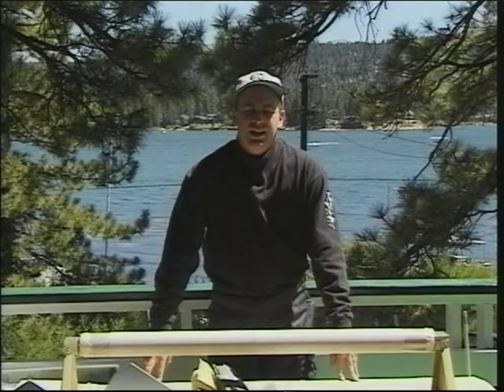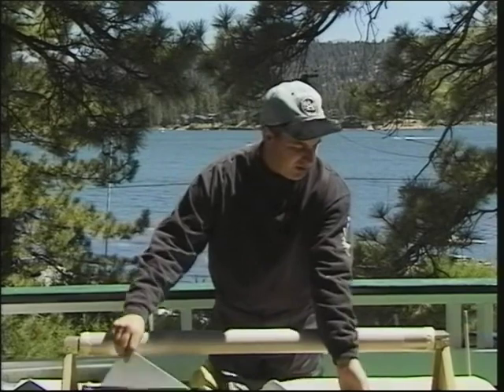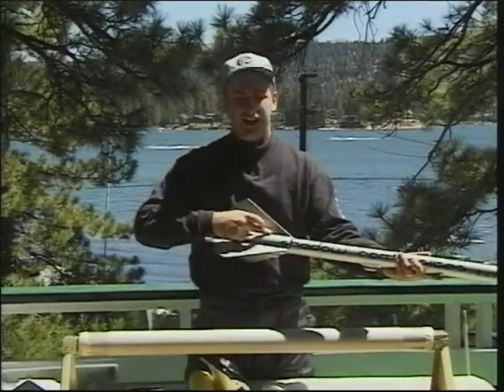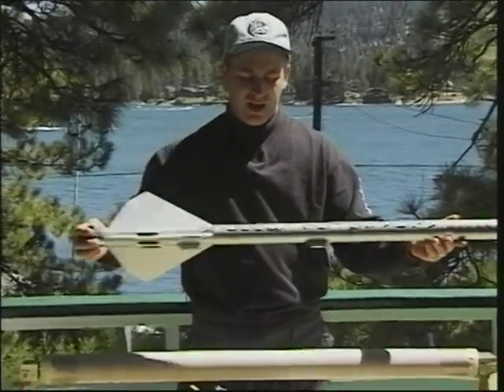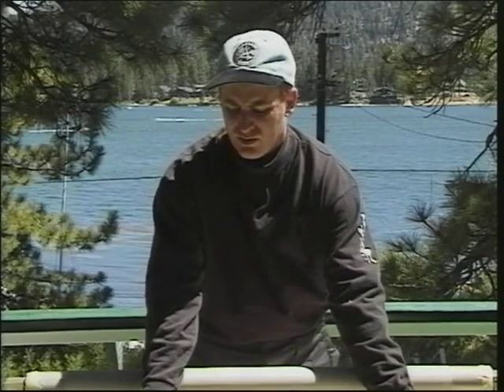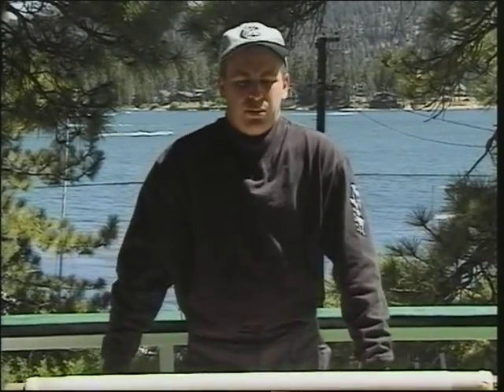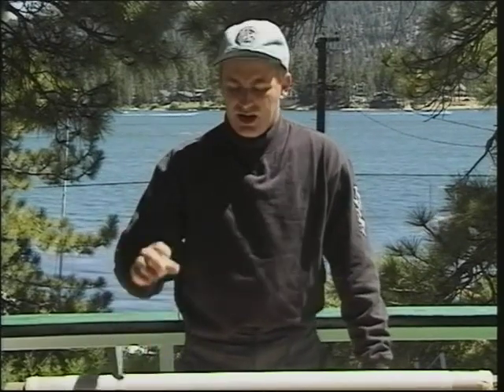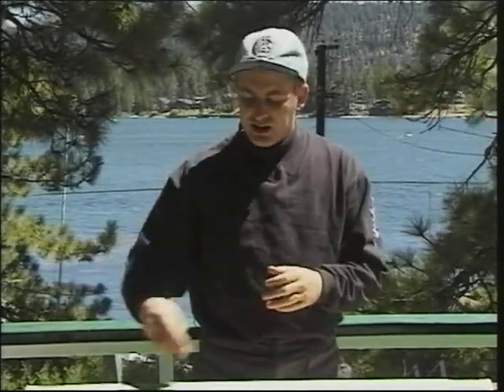So when you're creating things like fillets, and here I've got a couple of the Shadow Composites Raven rockets, the little fillet areas that attach the fins to the airframe, there's a couple different ways of going about that. If you're creating an epoxy structure on your airframe tube, you want to use a fillet material that's made out of epoxy as well. When you rough up the structure of the glass surface after you've completed that, that'll provide a good mechanical tooth to it, so the fillet material will grab onto it. But you also want somewhat of a chemical bond between your fillet material and your airframe. So there's a couple different ways you can go about that.